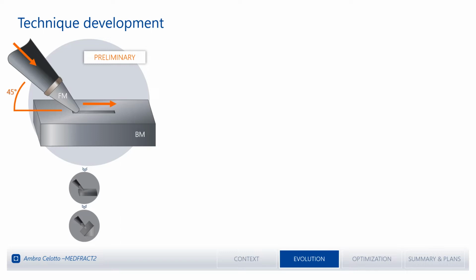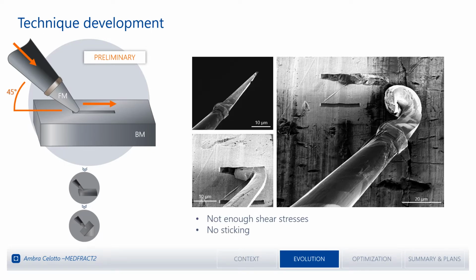The very preliminary attempt consisted in feeding the filler metal in a groove dug in the base metal, so basically pushing the hybrid needle inside a groove. But in reality, the needle turned out to be very, very sharp, and this didn't create the conditions for achieving enough shear stresses between the walls of the groove and the sides of the tip. And this led to having no sticking at all between the parts.